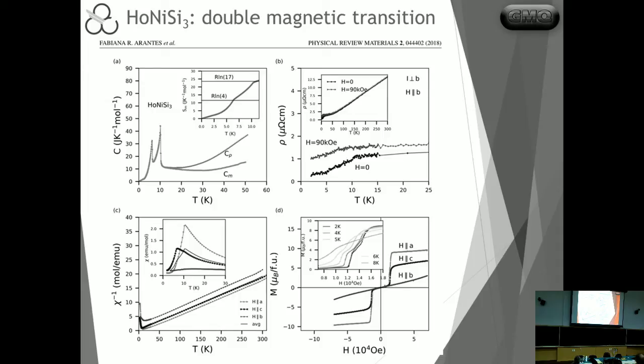So when we apply the field along the A-axis, we have a higher TN around 11, and along the C-axis, there's a lower TN. This was actually quite surprising. It's hard to explain how this can happen, to have different TNs.